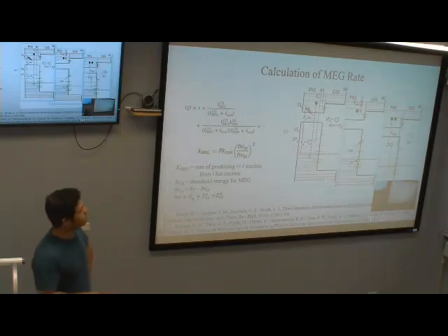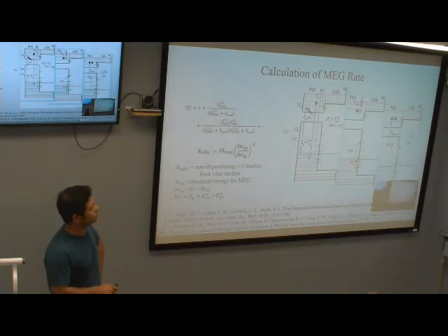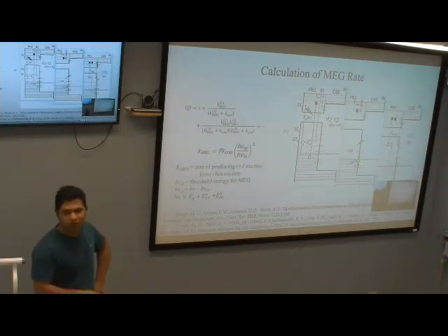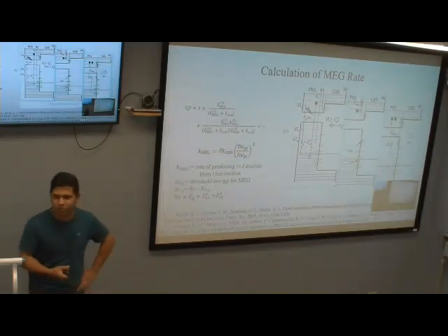Another focus is that the offset of the LUMO of the lead part and cadmium part is very small compared to the valence band offset. So all this mechanism happens on the valence band, I mean, related to the hole.